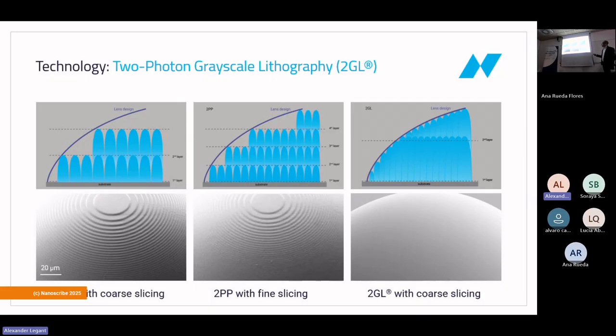And that's the reason why we use this two-photon grayscale lithography, 2GL, and can still expose quite big layers, and just use the 2GL effect on the slopes, to have the same speed as with big steps, but at the same time the surface roughness goes down to around 10 nanometers.